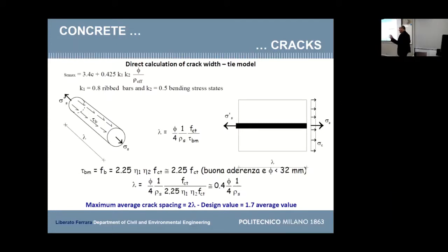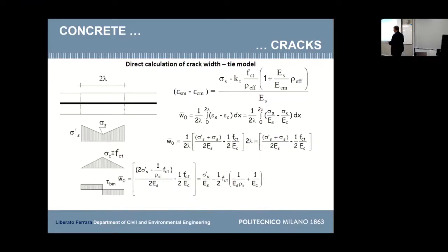But given a certain amount of reinforcement that you must put there for other requirements, there is this parameter that you have to take into account, which is the diameter of the bar. The smaller the bar, which means also the higher number of bars that you have to put in there to get the same area, the smaller is this transfer length. This transfer length, anyway, is also related to the crack width.